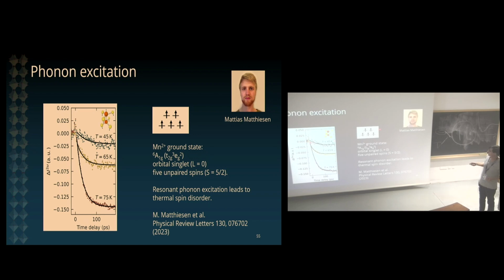So these are measurements done by Matthias, which is tracking second harmonic versus time after he excited this specific lattice mode of manganese thiophosphate in the antiferromagnetic state, and you see that there is a change in the intensity of the second harmonic signal, and you see interestingly that now you are depressing your signal, so you are strongly reducing the antiferromagnetic order, and you do so in a span of 100 picoseconds. You are disordering your antiferromagnetic lattice. Okay, so this is in contrast with all the coherent dynamics that I showed you before in the system. So what's so different between these two systems?